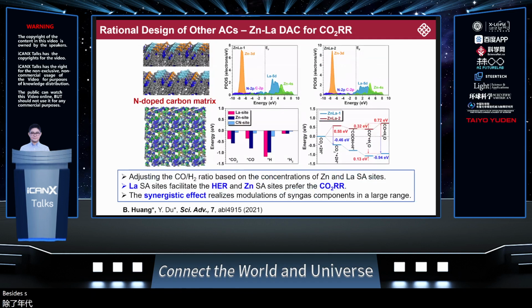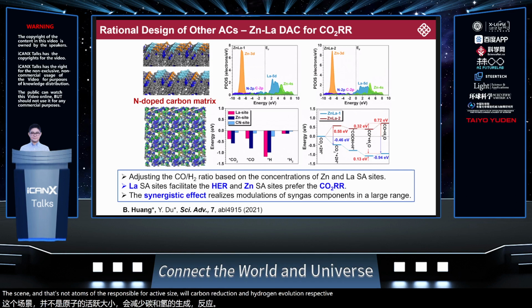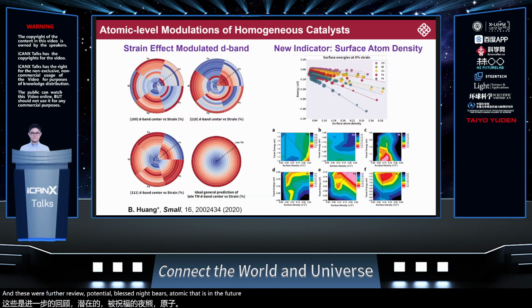Besides SAC, we also successfully achieved the zinc and the lanthanide DAC with Nankai University. And this DAC shows high performances for the syngas generation. The zinc and the lanthanide atoms are responsible for the active sites for carbon reduction and hydrogen evolution reaction, respectively. By adjusting the ratio of these two metal sites, the components of the syngas can be modulated in a large range. And this work further reveals the great potential of lanthanide-based atomic catalysts in future applications.